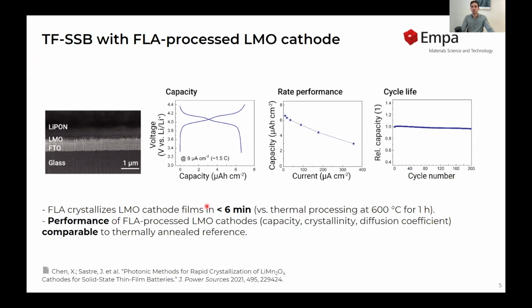So in conclusion, we observed that FLA is capable of crystallizing LMO cathode films in short times, below 6 minutes, which is much less than the 1 hour used in standard thermal annealing processes. And the performance of such LMO films is comparable or even better than the thermally annealed reference.